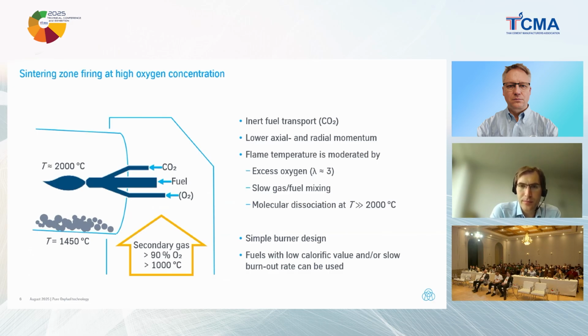And then due to the high oxygen concentration, the burner design can be a bit more simplistic than nowadays high momentum burners that are designed, for example, to be used with secondary fuels, due to the fact that the high oxygen concentration always allows a good ignition and combustion of the fuel. So by this concept, it's well feasible to run the sintering zone with this very high oxygen concentration.